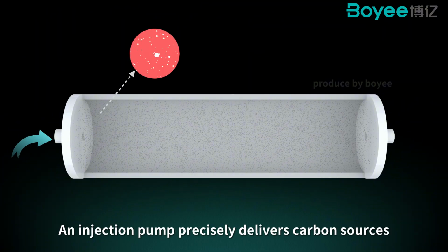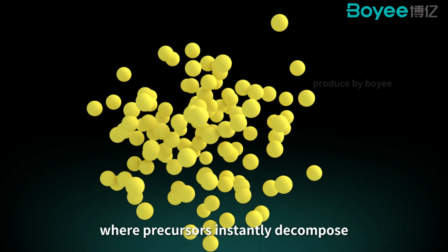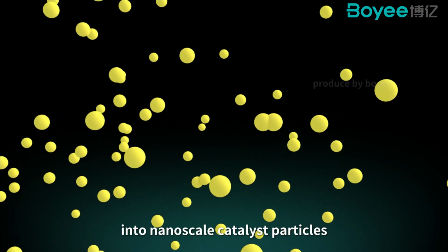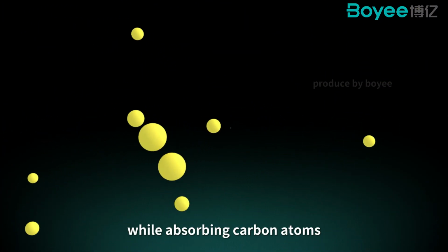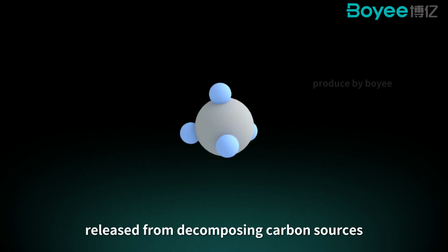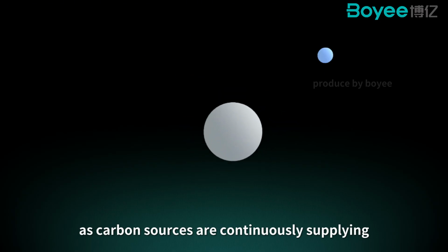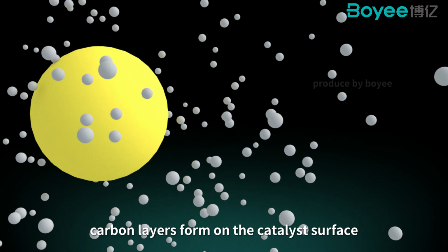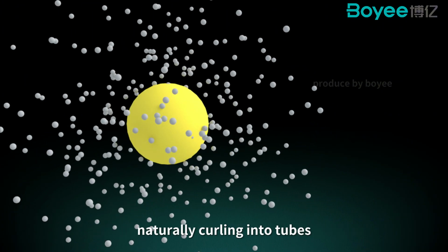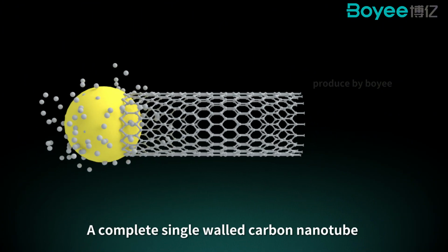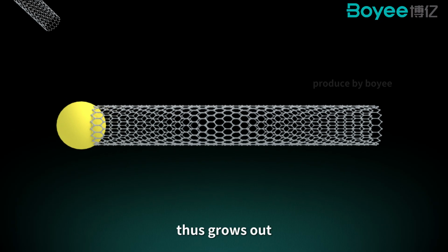An injection pump precisely delivers carbon sources mixed with ferrocene into the furnace, where precursors instantly decompose into nanoscale catalyst particles. These particles float while absorbing carbon atoms released from decomposing carbon sources. As carbon sources are continuously supplied, carbon layers form on the catalyst surface, naturally curling into tubes. A complete single-walled carbon nanotube thus grows out.